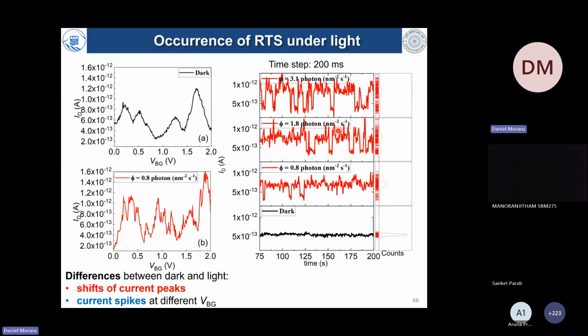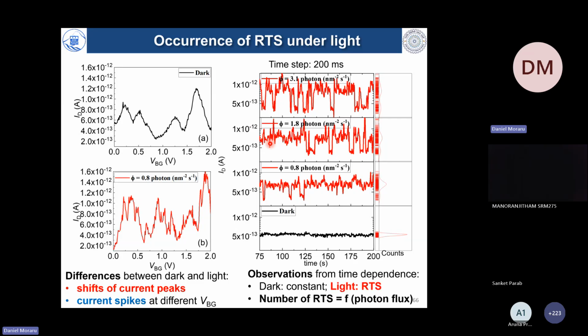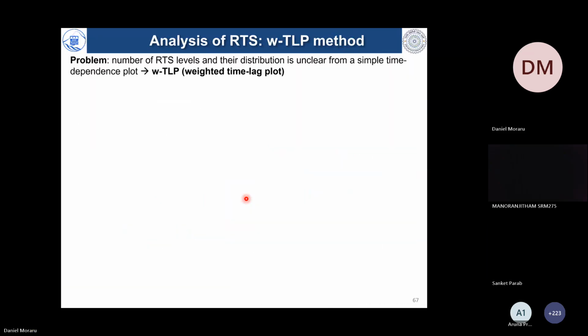More importantly, however, is what happens when we change the photon flux. The number of changes of current, of a so-called RTS, also changes significantly. If in dark we see practically no change, under light we see RTS, and it depends on the photon flux. And that's a signature that we are sensing the photons absorbed here.